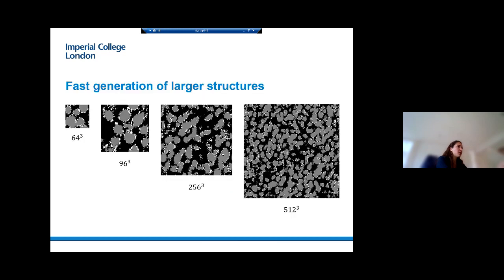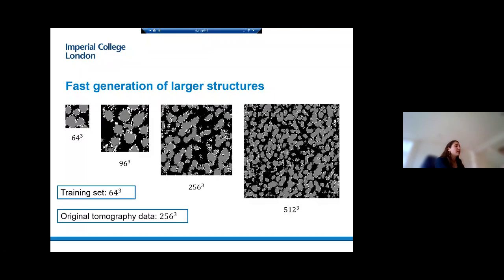Right, another important property of these generated images is that not only can we generate the small training set samples, we can also generate images as large as we want. For example, in this case, you can see that we can generate images up to basically the size that we want. And one interesting thing is that the original tomographic data was only 256 cube pixels. And with the generator, we're able to make images that are twice the size of the original data.